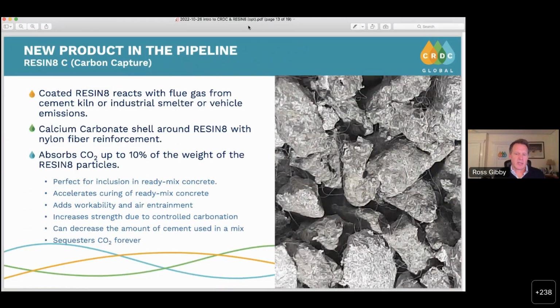So this is what I mentioned and alluded to earlier. A press release just came out this morning, a formal press release announcing this new technology. What this is: we take the original core resonate particle, which does have that open cell structure, which absorbs material. And we take that and we coat it with a cement paste and expose it to an emission source. In certain cases, it's literally just an emission source out of a vehicle, a truck or a car. And it absorbs the CO2. The calcium hydroxide in the cement paste absorbs CO2 and converts it into calcium carbonate. Calcium carbonate is literally just limestone. So what happens is it creates a limestone shell around the outside of the core resonate particle.